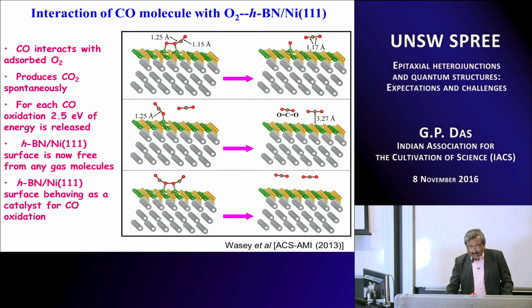happens? Let us see. So now I bring a CO molecule to the surface, and it is interesting that the CO molecule takes away one of the oxygen atoms from the activated OO bond and goes away as CO2. You can see that. When the next CO comes, it takes away an oxygen and becomes CO2, leaving behind one oxygen. When the next CO comes, it takes away that oxygen and again goes away. So finally, both the CO2 go away, leaving behind the pristine HBN sheet deposited on nickel 111.